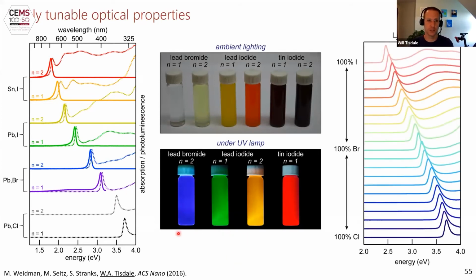And you're not restricted to just these discrete peaks. By doing any stoichiometric ratio you like, any alloying, from pure iodide to iodide bromide mixtures to pure bromide, bromide chloride mixtures to pure chloride, you can continuously tune the band gap of these materials.